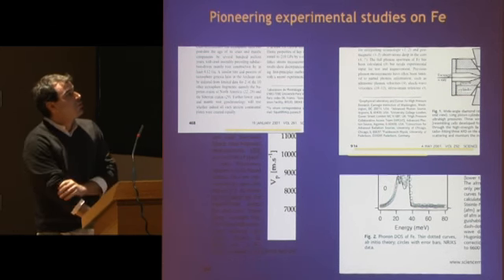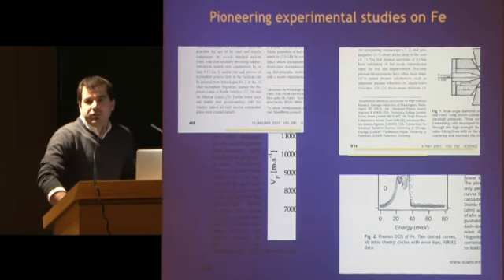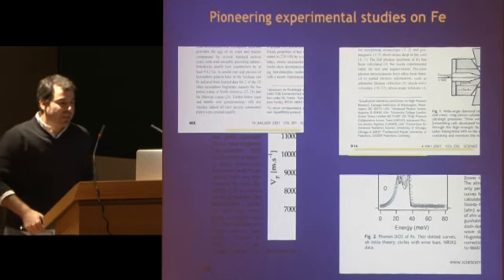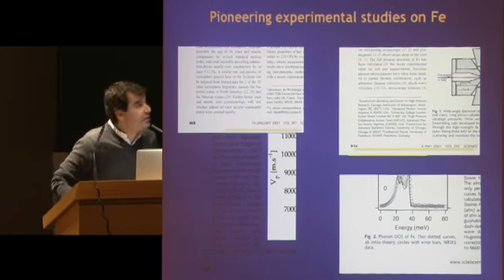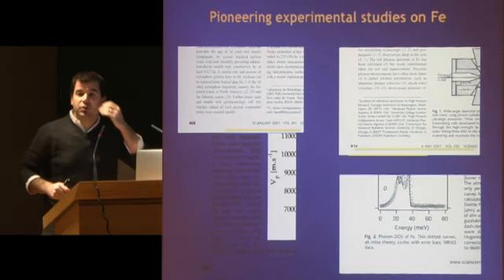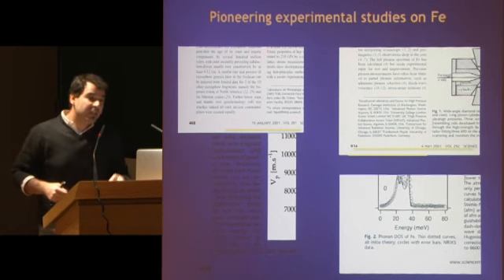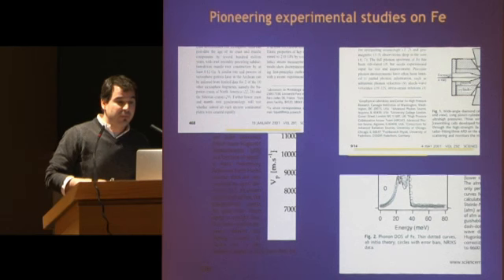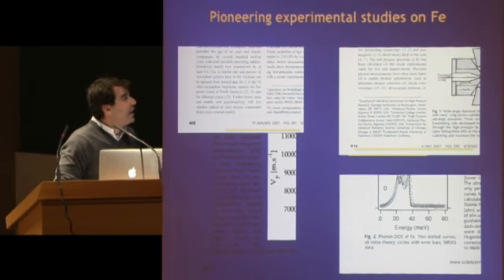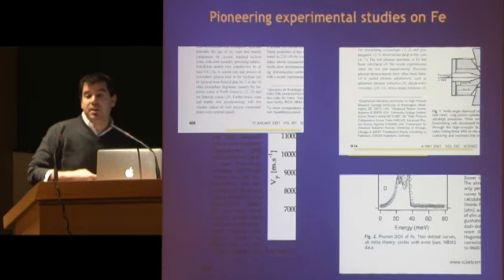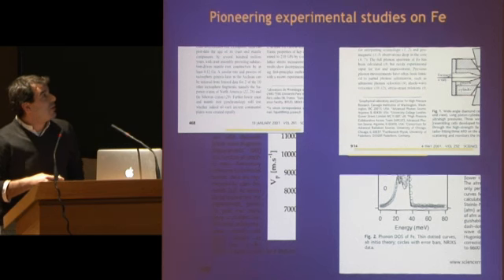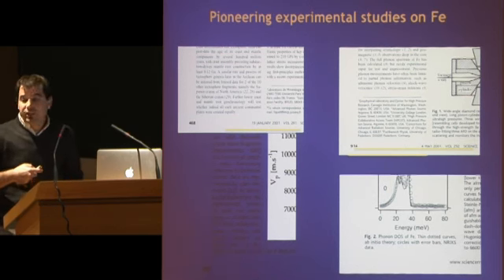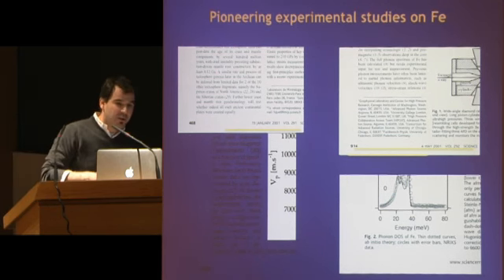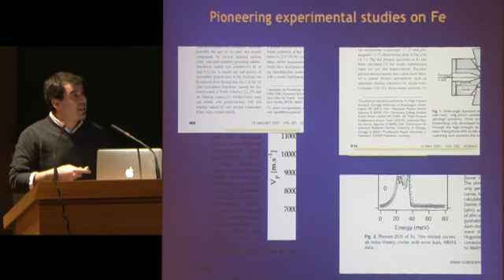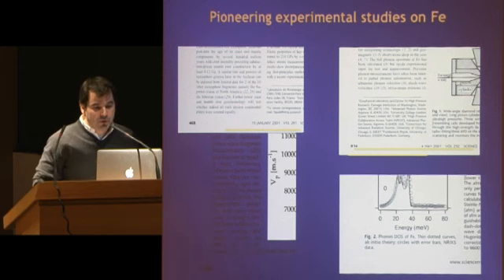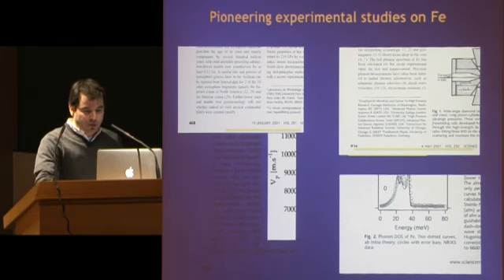I was just going to show two data sets that appeared in Science papers, one shortly after the other. One by inelastic neutron scattering and the second by nuclear resonant inelastic X-ray scattering. This work really opened in 2001 the possibility of high pressure measurement and sound velocity measurement at megabar pressure. And they generated big interest, especially because one work by Fiquet and co-workers suggested iron velocity to be lower, so that we need to add light elements to match the seismic observation, while the work of Mao and co-workers had an opposite conclusion.